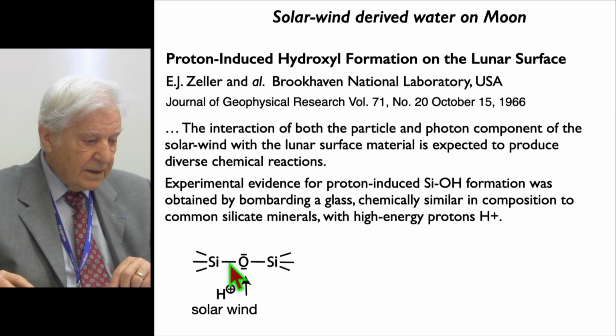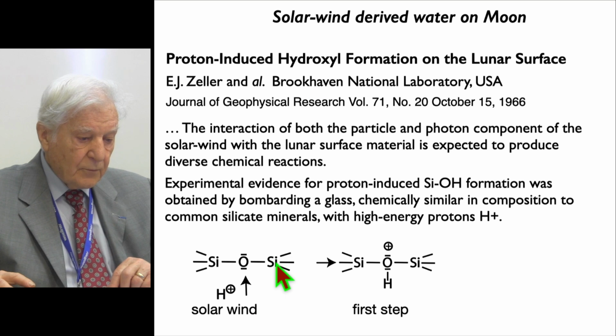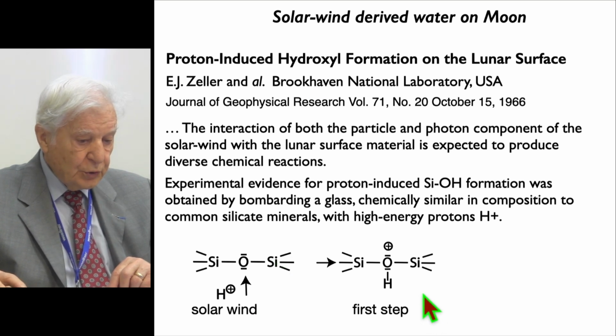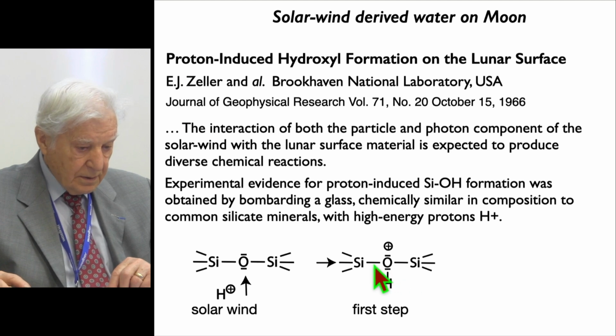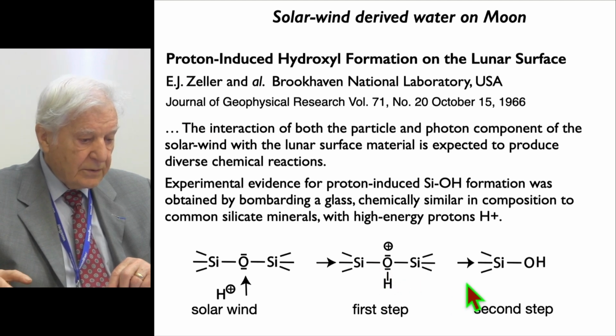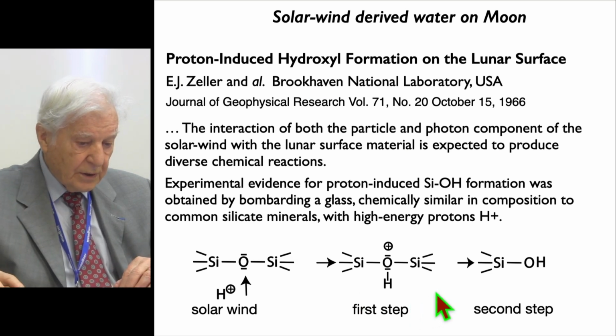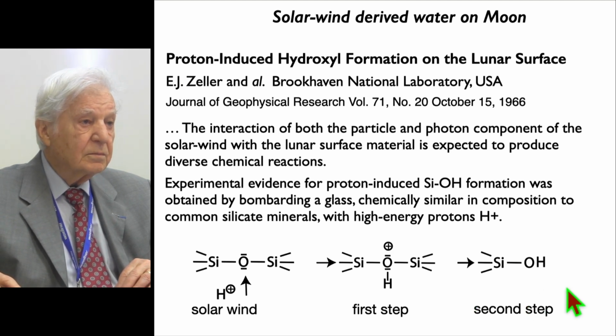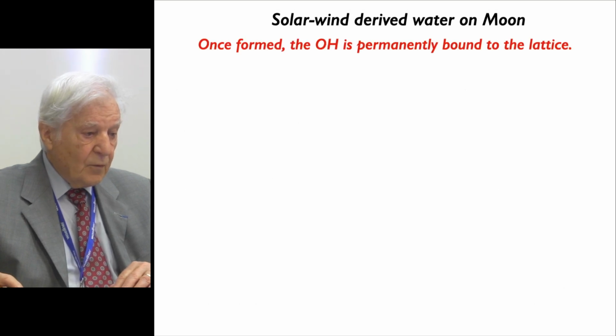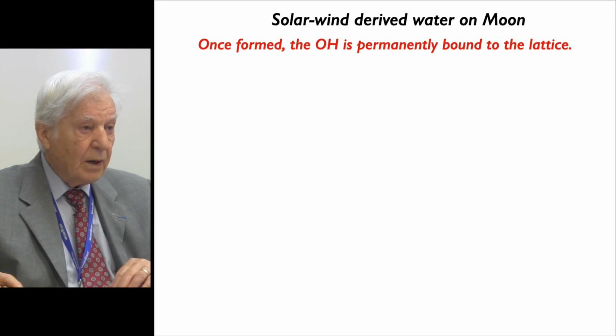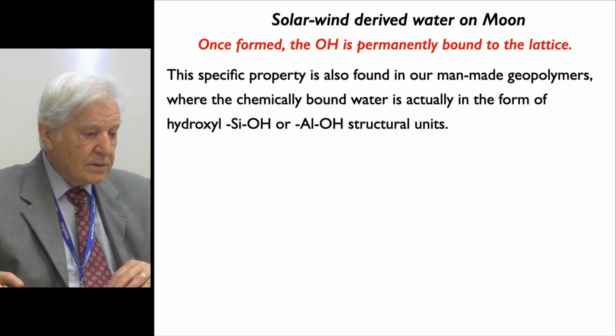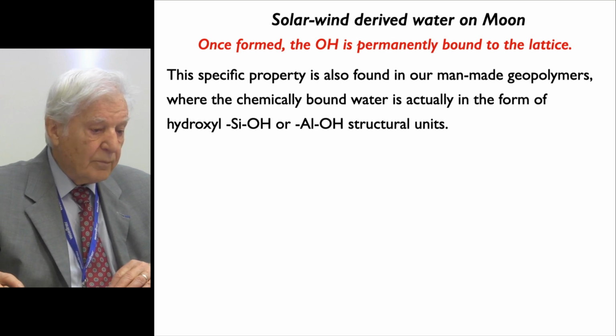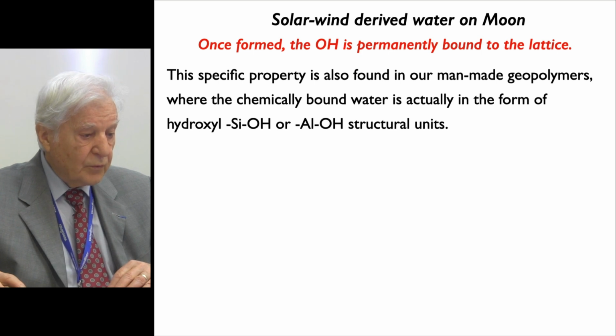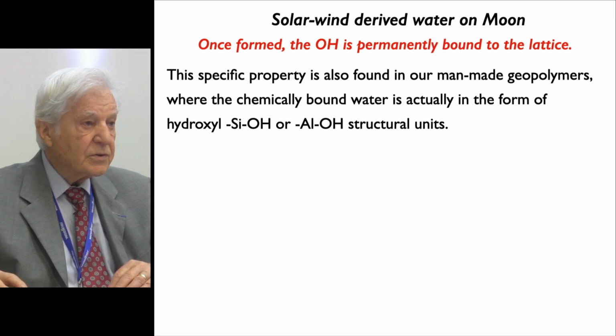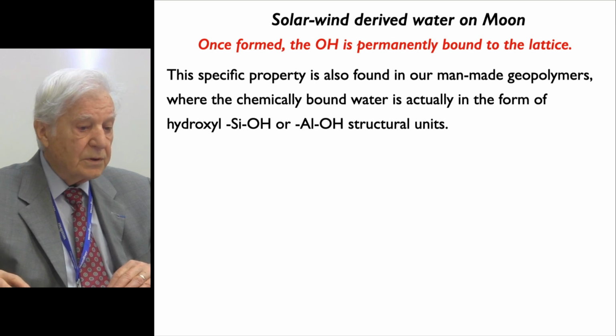hits the silicate minerals. The first step, we have the attachment of the proton H+ to the lone electron pair of the siloxane oxygen. And the second step, after several reactions leading to the decomposition of the oxonium complex with the formation of the silanol unit OH continuously. Once formed, the OH is permanently bound to the lattice. This specific property is also found in our man-made geopolymers, where the chemically bound water is actually in the form of hydroxyl SiOH or ALOH structural units.